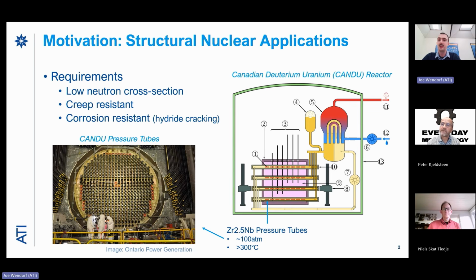And any alloy that has a lot of zirconium will accomplish that, although there are some impurities that you really need to keep low. In particular, hafnium is an impurity element that is in zirconium ore that is very strongly neutron absorbing, and so we go through a lot of effort to take all the hafnium out that we can. Yeah, is it like lead? That's also an absorber, isn't it? Yes, I'm not sure.